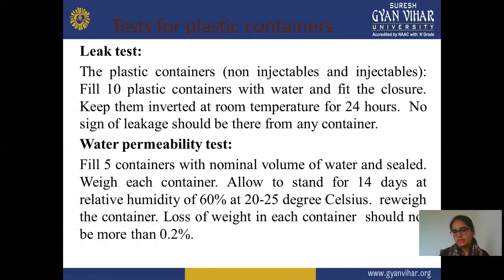Next is tests for plastic container. We already covered glass material tests. Here we are performing two tests according to USP and IP. The first test for plastic material is the leak test. This test is for plastic containers for both injectable and non-injectable formulations, parenteral as well as non-parenteral type. Fill 10 plastic containers with water and fit the closure, keep them inverted at room temperature.